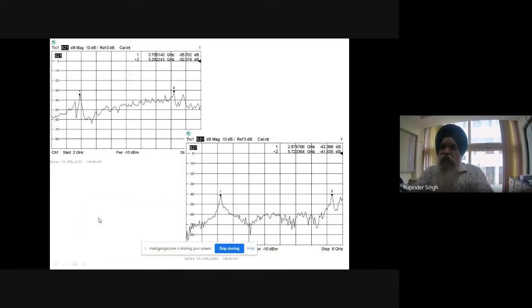We tried to see the effect on the VNA, and we observed the first peak at 2.75 and 5.28. And once we add the bakelite into it, this peak was shifted to the right, so 2.8 to 5.72. Right, so we are interested in making an antenna up to 2.45 gigahertz frequency.